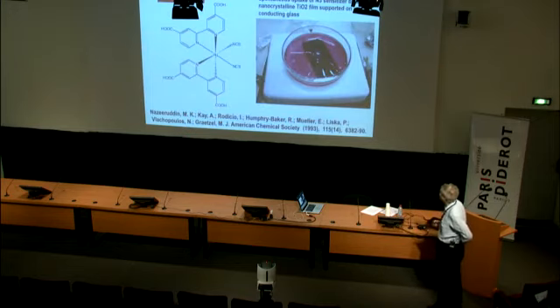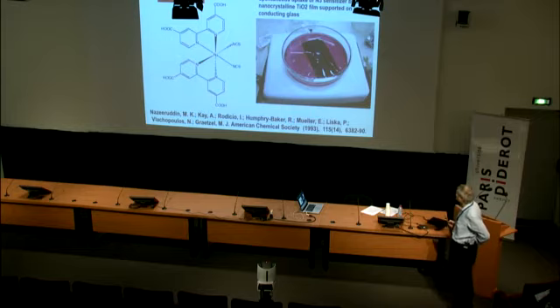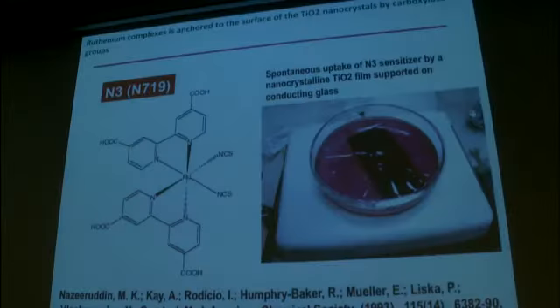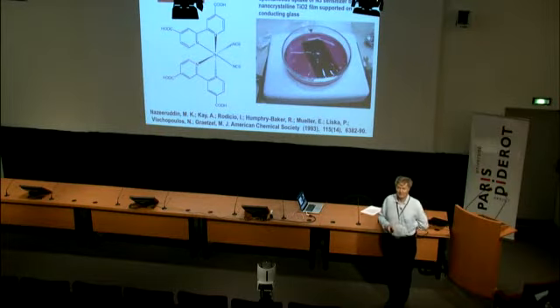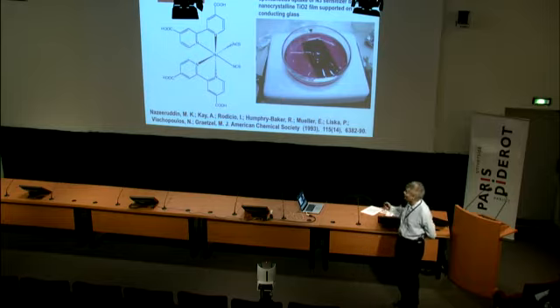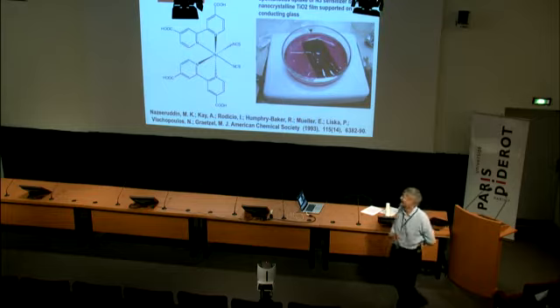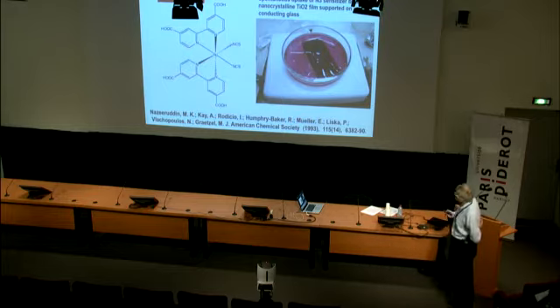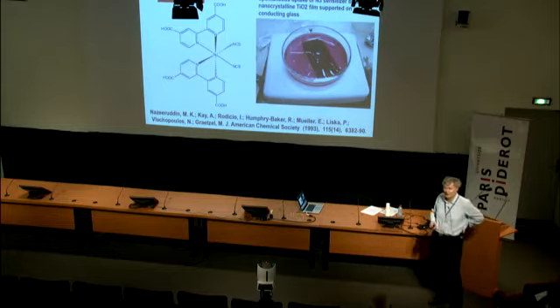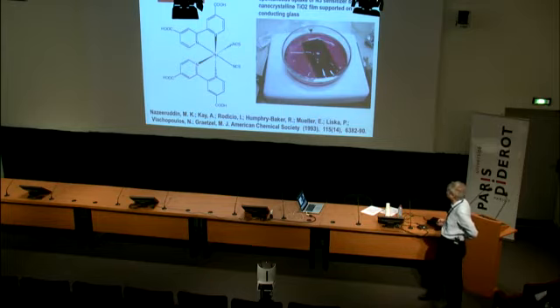And this now shows the dye structure again. And we have here the picture where we just put the film in the dye solution and see how it turns dark. That means the self-assembly works. The film is now adsorbed. The dye is adsorbed on the film through those carboxylate groups that coordinate with surface titanium ions. And that makes this very dark electrode, and that's the photoelectrode we're using for the dye-sensitized solar cell.